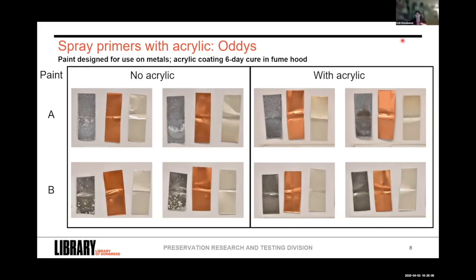both paints, the acrylic top coat was very beneficial in reducing what would have been the overall off-gassing, but the Oddy test was showing us that it really does matter which paint is being used as your undercoat. Even if you're putting a coating on something, you still need to be careful about what it is coating. Putting an acrylic coating does show promise and benefit. I believe that's what actually was done on the final mounts that went into the exhibit, but it's definitely not put a coating on it and everything will be 100% fine all the time, which was interesting to see with